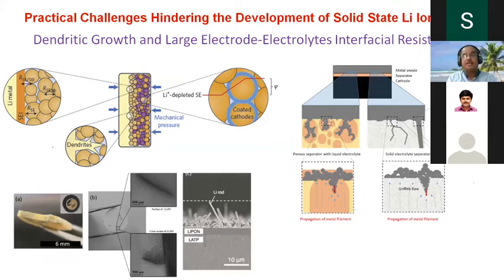Imagine this is the dendrite growth at the lithium electrode interface on the anode side. Lithium is highly reactive. Whenever there's a small gap in the grain boundary, it starts to penetrate. You can see here, then like this, then this one. So a lot of theory came into the picture.